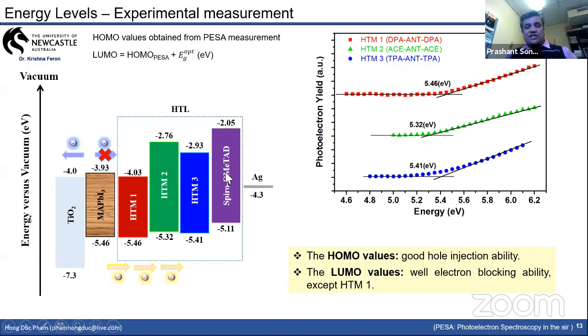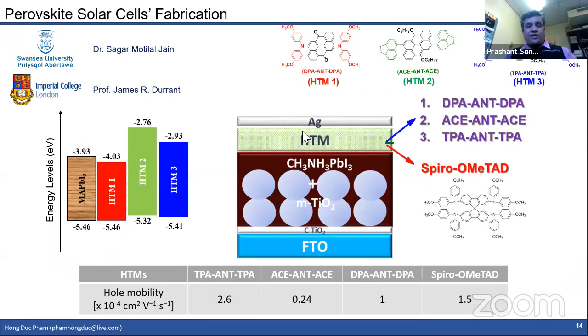And again, comparing this with the standard mesoporous TiO2, here I just showed the energy diagram. So when we utilized these 3 materials, particularly HTM2 and 3, we got a very high performance, whereas HTM1 has a bit of average performance. But here is the standard mesoporous device configuration. Instead of spiro, we utilized these 3 materials in this device. And the hole mobility of this material, you can see that for all of the 3 materials, the highest hole mobility which we got was for the TPA-ANT-TPA, which is 2.6 times 10 raised to minus 4, whereas the spiro shows 1.5.